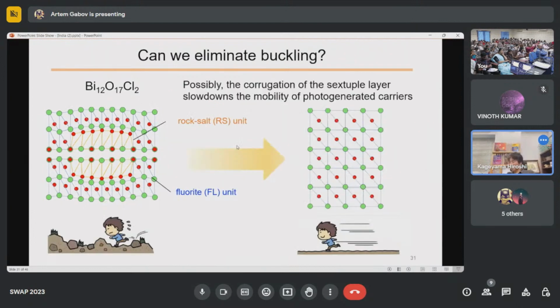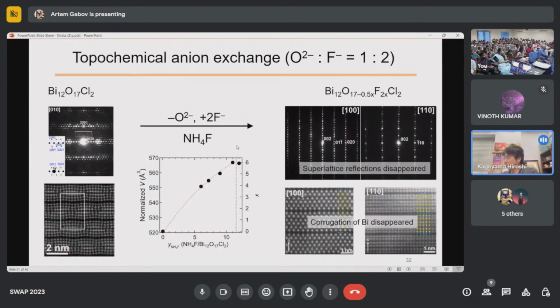Okay. But thinking about photocatalysis, maybe such wavy behavior is not so good. Maybe you can see from this cartoon, the wavy structure is very bad for photogenerated holes and photogenerated electrons. Maybe a flat surface, a flat layer, could be ideal for photocatalytic activity. Okay. Then we wanted to consider some chemical reactions to remove such modulations. And in fact, we did oxygen-fluorine anion exchange reactions. It's a 1-2 anion exchange because of the charge neutrality.